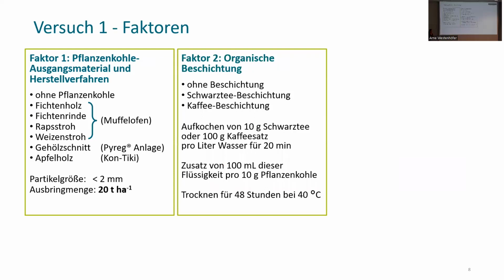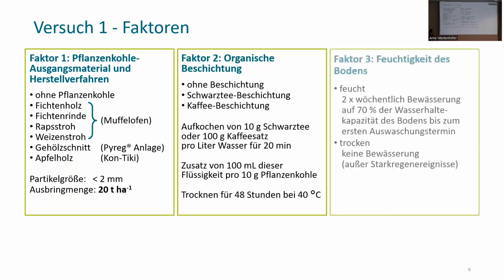Then there's the second factor, the organic coating we tried to bring about. We had a control variant without coating, and one variant with black tea coating and coffee coating. We used coffee grounds that we had collected before from kind donors. We cooked it for 20 minutes, and this liquid was applied to biochar. It dried there 2 days in a drying chamber.